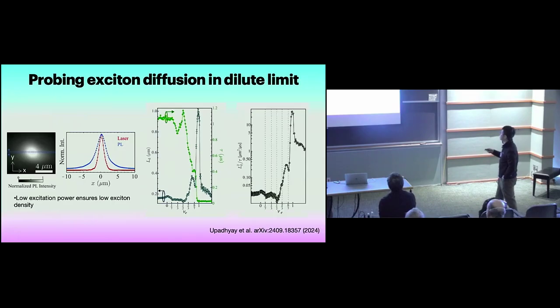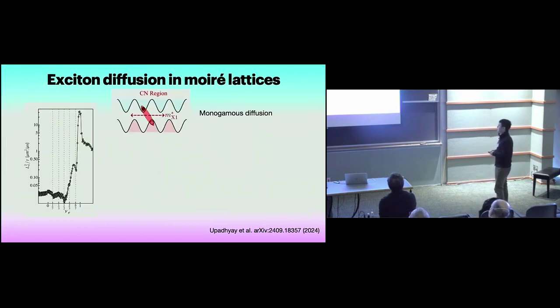So we plot this parameter that's related to diffusivity, which is the diffusion length squared divided by the lifetime. And related to diffusivity, we find that exciton diffusivity is actually enhanced by almost 2 orders of magnitude at the Mott transition, at this electronic Mott transition. So this was really very surprising for us. And Mohammad and Michael Knap, they came up with, I think, a very elegant idea to explain this phenomenon.